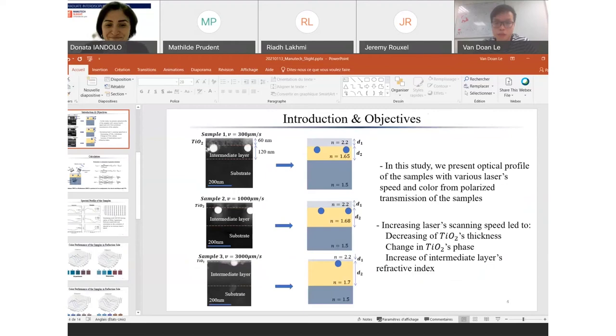Yes. I choose my parameters based on the SEM and TEM images of the sample. As I observe in the SEM and TEM, when I increase the laser scanning speed, the formation of the titanium film changes, and the phase change means that the refractive index increases, but the inhomogeneity decreases. So I can approximate the top layer with the same refractive index. And from the mapping in TEM, I can see the intermediate layer arises from the combining of the titanium particles with the silicate. So I can choose the refractive index to increase as we increase the laser scanning speed. To conclude, it's just based on the SEM and TEM images.